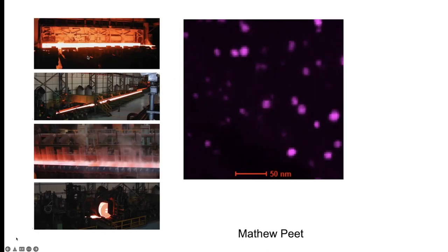So this is classic thermomechanical processing, where you hot roll the steel and you control the rolling conditions so that when the material leaves the hot rolling line, the austenite grains are not able to recrystallize. So you end up with very pancaked grains of austenite, and you've added some sort of microalloying addition which prevents those grains from recrystallizing even more, okay? And then you will get extremely fine austenite grains, and therefore you will get extremely fine martensite.